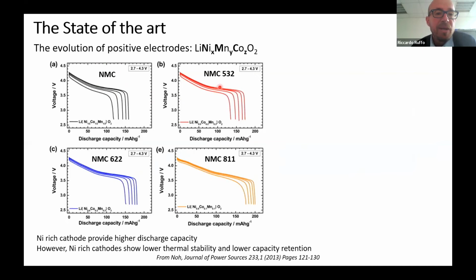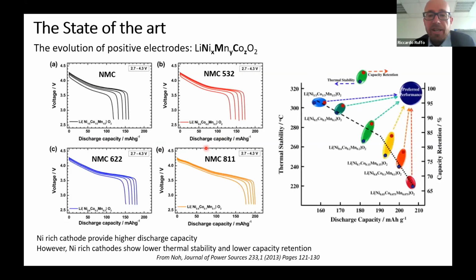We try to increase the amount of nickel, which has very good electrochemical properties, and we can try to reduce the amount of cobalt here. But we pay in this direction because the less cobalt you have in your system, the lower is the reversibility of the reaction. So you pay something in terms of capacity retention, and also the thermal stability is affected. While if you increase the nickel amount, you can get very high discharge capacity, but you have a less reversible system and a less chemically stable system. So we always have this trade-off between reversibility, lifetime of the battery, and properties in terms of energy density.